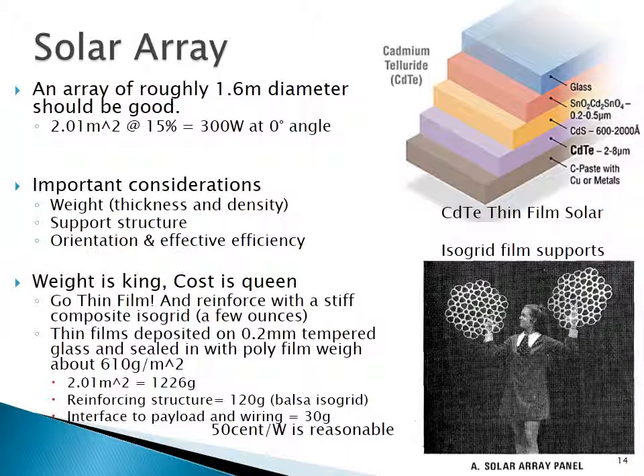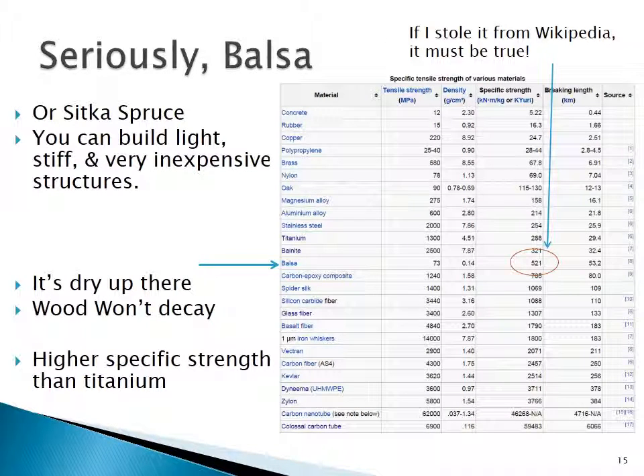Thin films you can deposit on glass, and you can get very thin glass. Tempered glass in the 0.2 millimeter range is easily commercially available. So you can just deposit thin film on glass, seal it in, and then mount that to a balsa wood isogrid. Isogrid structures are very efficient, and balsa wood is an extraordinary structural material when you look at high stiffness and low weight. And I'm totally serious about that. Some people think I'm crazy when I say that, but balsa wood and Sitka spruce are two excellent choices.